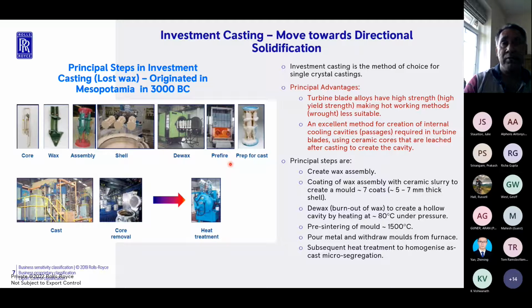The other thing, if you remember, I did mention was, when you look at how you develop alloys for higher temperature capability, one of the ways is to put complicated cooling passages. So you cool the blade, you either put a TBC, or alternatively, you have internal cooling passages where you flow air. Now, such intricate cooling passages cannot be produced by any other method apart from investment casting. So again, go back to the same old point, rather than me sounding like a broken record, that the method of manufacture and the temperature capability of the material in many ways dictates the method of manufacture of that component. So for turbine blade components or turbine vanes, the method of manufacture is investment casting.